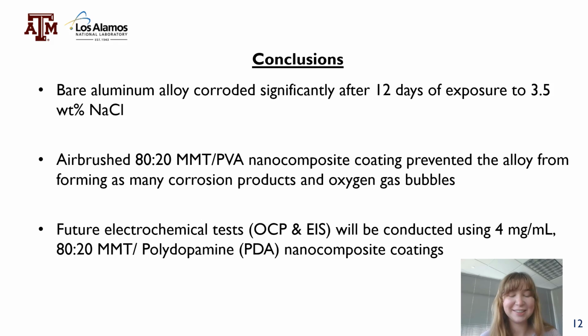In conclusion, the bare aluminum alloy coupons corroded significantly after 12 days of exposure to 3.5 weight % NaCl solution. But our airbrushed 80-20 ratio of MMT PVA nanocomposite coating prevented the aluminum alloy from forming as many corrosion products or as many oxygen gas bubbles over a 12-day time period.